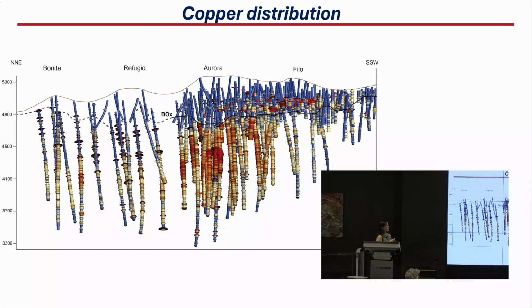But now let's think about how the minerals and, in this case, the metals are distributed. This is the same cross-section with the drill hole data. In this case, it's copper. We can see that it actually has a lot of copper, in some areas more than 1% copper. I also added the bottom of the oxidation, because we can clearly see that we have the oxide zone and what is called the high-grade sulfide zone.